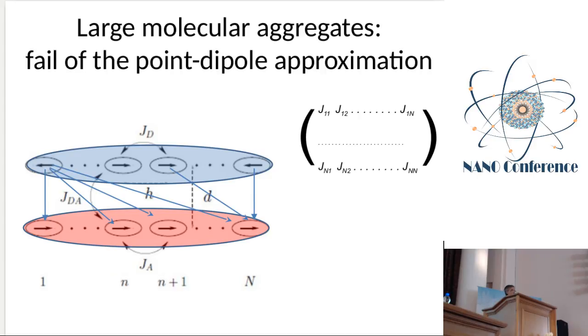In large aggregates, there is some specific situation, because the size of aggregates can be comparable with the distance between the aggregates. In this case, the point dipole approximation cannot be applied, and we should consider each aggregate as a set of different dipoles which interact. So each dipole on the donor aggregate will interact with every dipole on the acceptor aggregate.